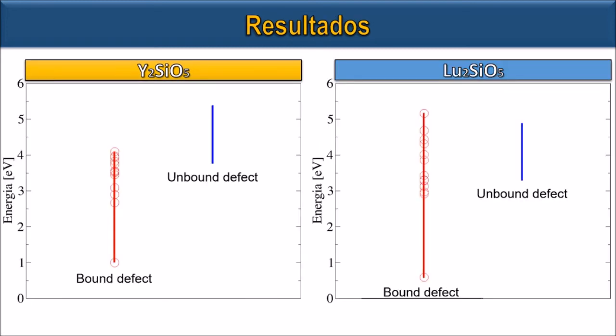The oxygen Frenkel defect, which had the lowest energy cost in both silicates, is formed by an oxygen vacancy and an interstitial oxygen. For this type of defect, in case these point defects, oxygen vacancies and interstitial oxygens, interact in the structure, which are called bound defects, most of the energies found are smaller than that obtained for the unbound condition, meaning that the close proximity of the interstitial to the vacancy reduces the total energetic cost due to the Coulomb interaction between the effectively charged defects.